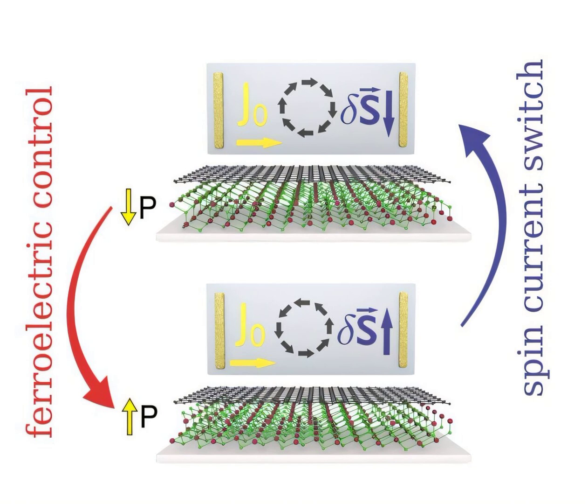Key findings: spin control via ferroelectric switching. The research team investigated graphene/In2Se3 heterostructures in both aligned (0 degrees) and twisted (5 degrees) configurations. Detailed electronic structure calculations revealed that reversing the ferroelectric polarization of In2Se3 reverses the charge-to-spin conversion coefficient, creating an electrical chirality switch for spin currents in graphene.